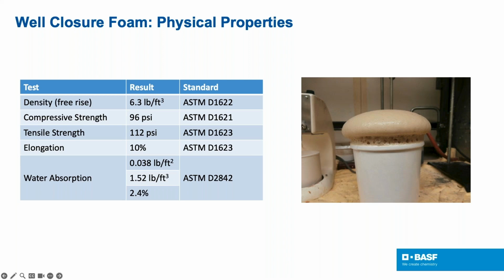But right now, density is around six pounds per cubic foot, compressive strength 96 psi, tensile strength 112. Elongation 10%, so definitely some flexibility, some ability to expand and contract, create a good seal. And again, these are all properties that we can modify based on the chemistry. And water absorption is low, helping to make sure that the product doesn't get waterlogged in wet applications. Next slide, please.